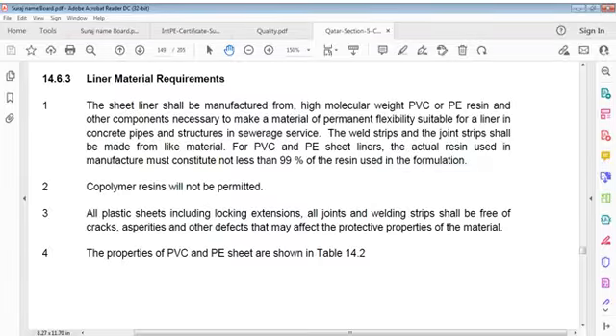Weld strips and joint strips shall be made from like materials for PVC and PE sheet liners. Actual resin used in manufacture must constitute not less than 99% of resin used in formulation.